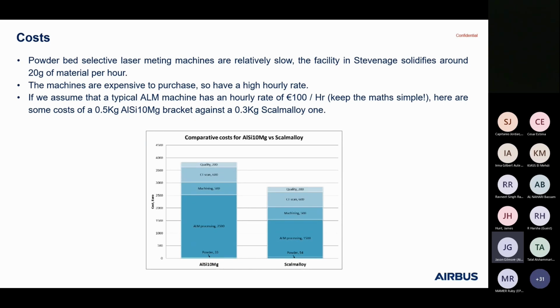So for investing in a more expensive material, and if you lightweight your designs, you can't just build the same geometry, you've got to lightweight it. Your big cost saving is attributed to the time on the machine, then all the other costs will be the same. So one of the key messages here, there is a thought that Scalmalloy is an expensive material. Yes, it is. But if you use the yield strength, nearly 3 times that of aluminium silicon 10 in the stress relief condition, you use it and you load the component up well, you stress it to a good limit, then you can lightweight and save money at the same time using Scalmalloy. So if we move to the next slide.